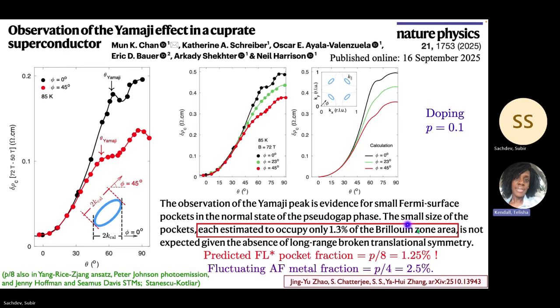Okay, so very excited. The other possible state is the spin density wave, which would give you p over 4, which is a factor of 2 off. So it's hard to believe that something's wrong by a factor of 2. So anyway, this is, I would say, the best evidence. First of all, it's nice to have in this field a quantitative prediction.